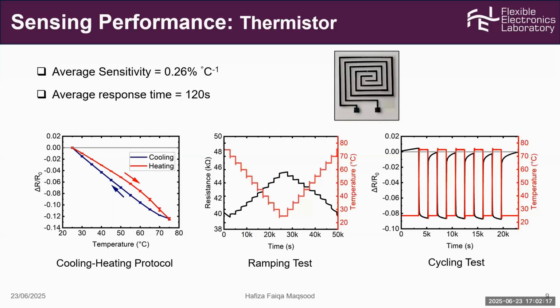And again, we performed the ramping test, where the temperature was increased in a discrete manner, and also the cyclic test, a 5-step cyclic test, where temperature increased and then reversed. In this way, our results were quite consistent in both these tests, showing the sensor reliability even under continuous and discrete changes of the temperature.